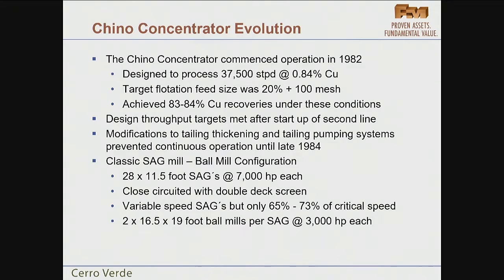The original plant was a classic SAG mill ball mill configuration with 28 by 11 and a half foot SAG mills, typical of the size of the day, 7,000 horsepower each. Closed circuited with double deck screens with the screen oversize returned to the SAG mill, and very modest variable speed range with the technology of the day, and twin 16 and a half by 19 foot ball mills per SAG mill at 3,000 horsepower each, so the power split was about 7,000 to 6,000, about equal.